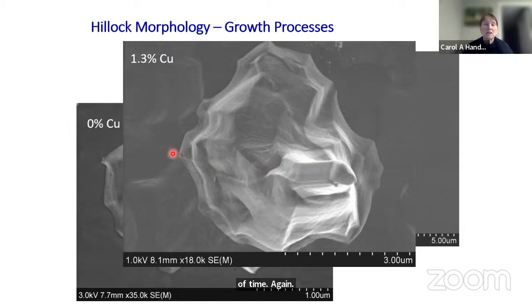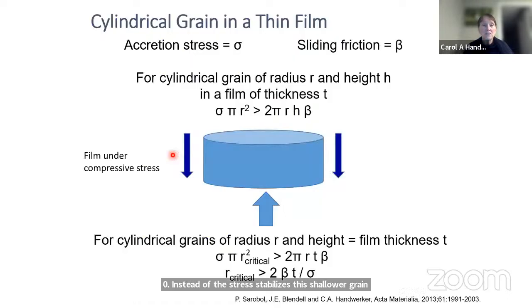And so it's important to note that if this were just migrating due to curvature, the shallow grain would actually shrink away to 0. And so the stress stabilizes this shallow grain and forces the grain boundary migration. So the way we've thought about this is a problem that is a trade-off between accretion of atoms at the bottom to relax the stress and grain boundary sliding.